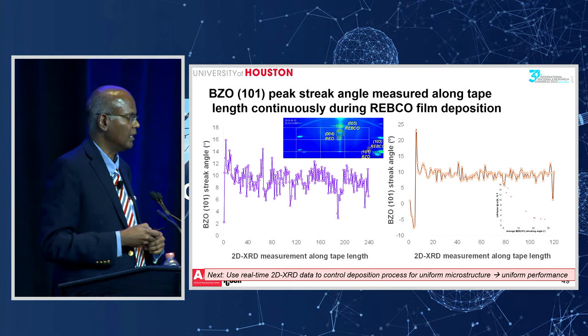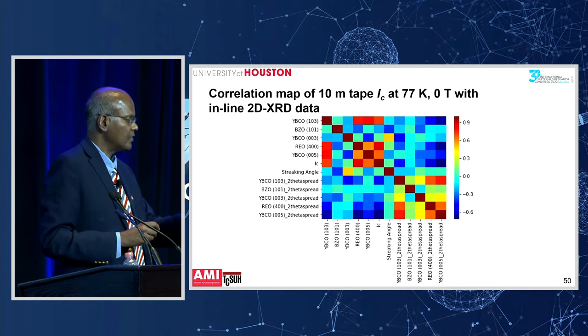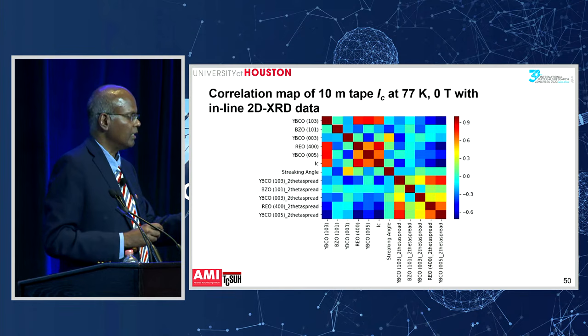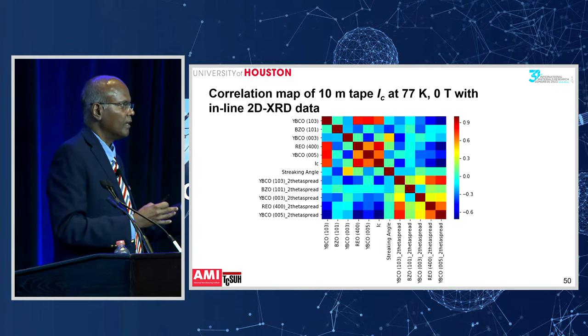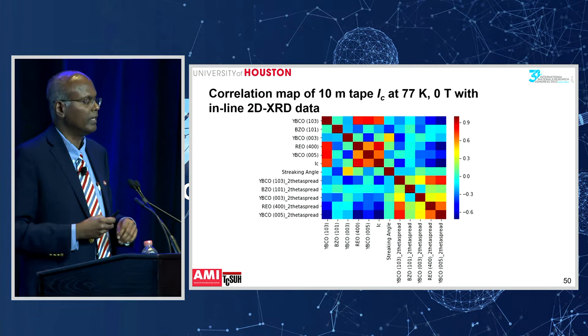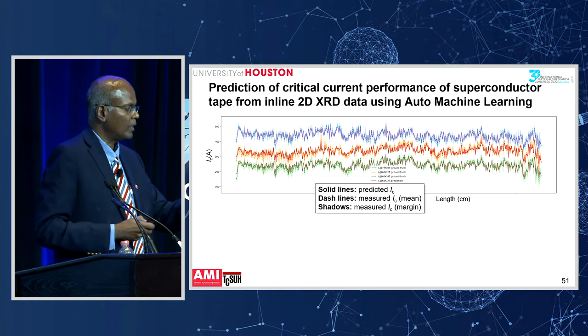Then, of course, you can create a nice map, a correlation map. So you can look at all these various features, the intensity of the various peaks. You can look at the spread of the various peaks. You can look at the critical current and see what really matches well with the critical current, right? You can get a good idea of that. And you can take a step further and implement some machine learning methods. And this is what I'm showing here.